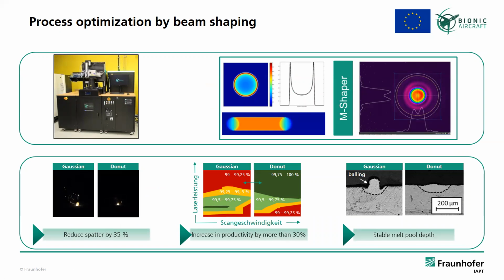And a third aspect that we're putting a lot of effort in, we started this within the Bionic Aircraft project that I presented before, is the field of non-conventional beam shapes. We have installed a beam shaper on our AconityLAB system here, which allows us to create such donut-shaped profiles or M-shaped profiles. And this in turn gives a more evenly distributed energy intake into the powder bed. And if you look at the videos here, you see that with a donut profile, you have a considerably lower amount of spattering, a much smoother process to work with. Also, when using the donut profile, you see here for the laser power and the scan speed, in the process field, you have a much larger process field to come to high densities and to integral parts.